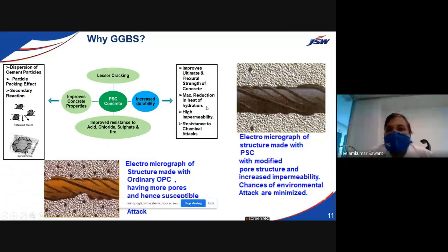Then there is maximum reduction in the heat of hydration because of the GGBS addition. It gives high impermeability because there are fewer voids and less porosity, and it also gives resistance to chemical attack. Whenever the concrete is cast with 100% OPC, after 3 to 4 years, if you see any pillar or RCC column in the stilt area of any residential building, it shows some vertical cracks on the surface of the body. That means the reinforcement steel bar is catching water from the environment through this porosity, and definitely rust will be there.